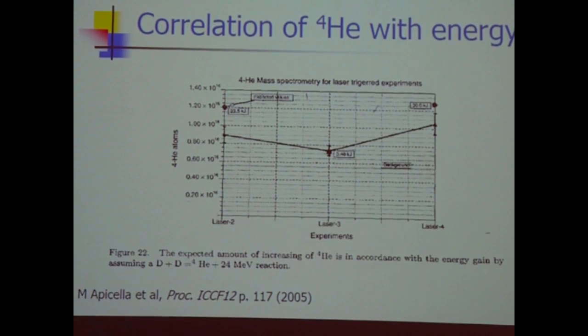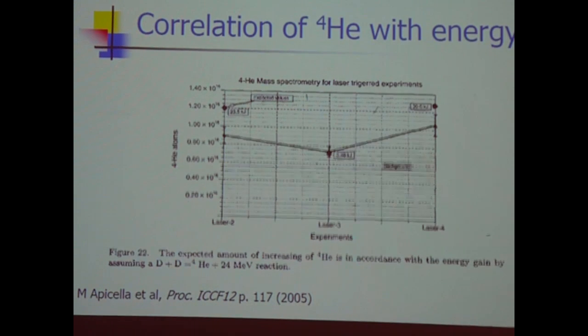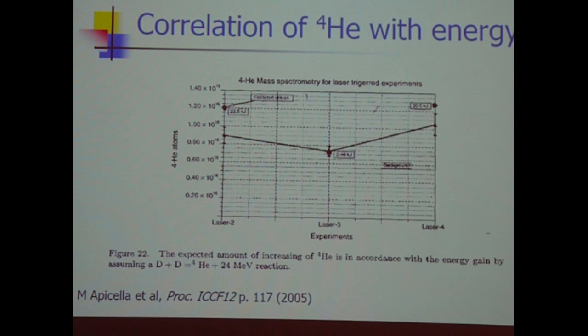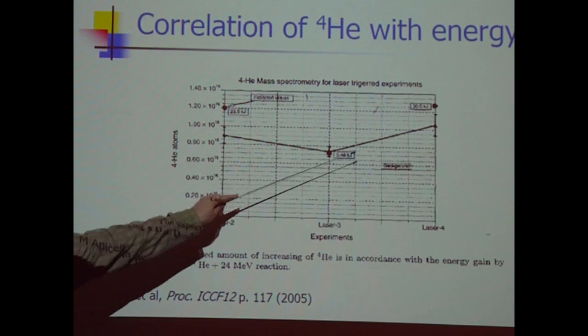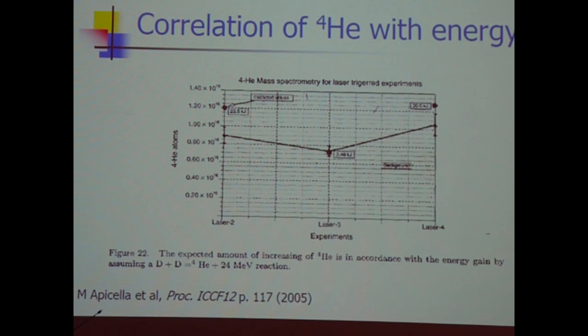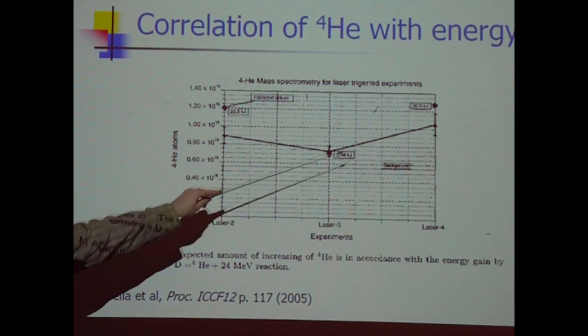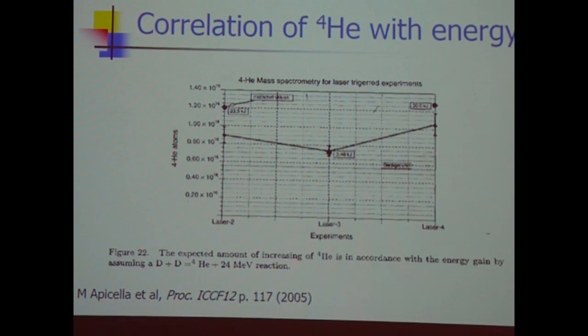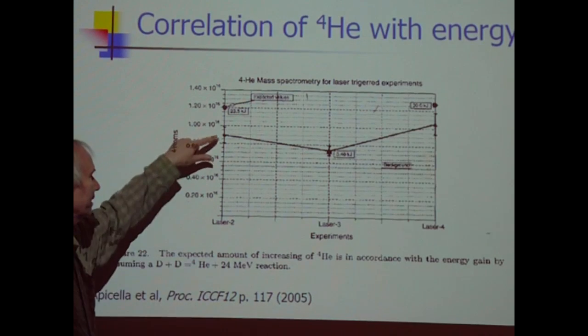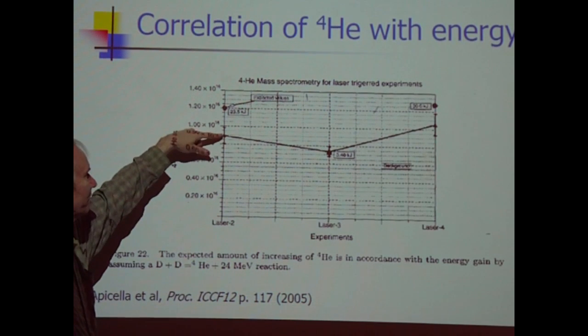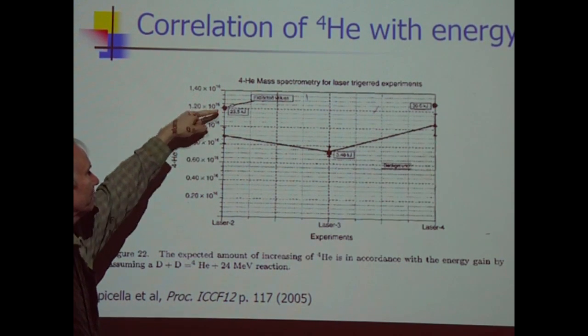There's one other experiment that's been performed that's qualitatively similar. At ENEA Frascati, this problem was of interest. They were doing laser excitation. So they had 3 experiments. In these experiments, the laser turns on and stimulates the excess heat. These 3 were done in a helium leak tight system. And in this case, this amount of excess heat was observed.